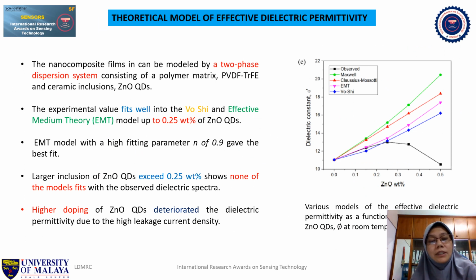We have also compared our experimental work with several theoretical models of effective dielectric permittivity, as shown in this figure here. So the nanocomposite films are modeled by a two-phase dispersion system consisting of the polymer matrix of PVDF-TrFE and the inclusion of zinc oxide quantum dots. So from this figure, we can see that Vo-Shi and effective medium theory fit well with the experimental result up to 0.25%. And EMT indicates that the fitting parameter obtained from the model is 0.9, which indicates that the quantum dot that we synthesized is not actually spherical, which contradicts what we have seen from TEM.